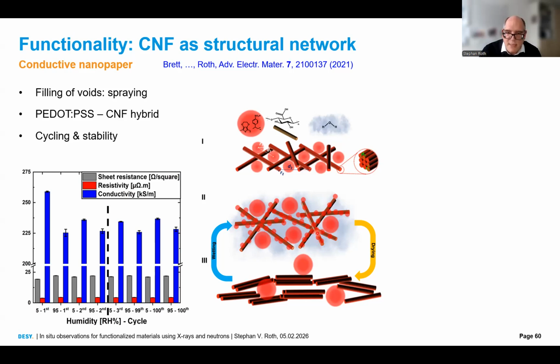Then we humidify. We see that from our GISAXS analysis, these particles become larger. We have a de-wetting on the surface of the CNF. In the first wetting cycle, we have a growing of these structures and a de-wetting and a slight reorientation of the CNF. Then we dry it. We have a reorientation. We have here a conductive path of PEDOT:PSS on the CNF, and these structures slightly grow in size again, especially compared to the beginning.